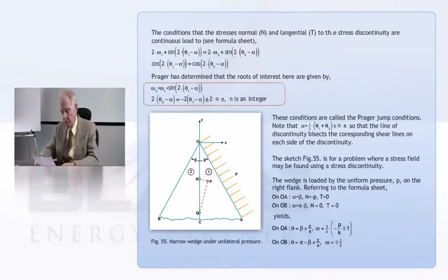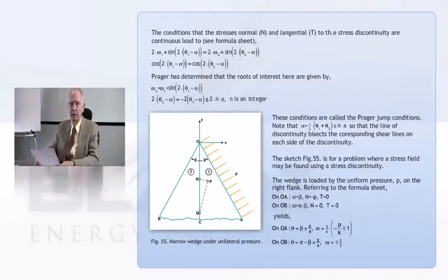The interesting thing about that is that the discontinuity, when you work things out, splits the angle between the corresponding shear lines. And that's very handy because geometrically you can work problems without thinking. And that's the next thing that we're going to do now, is we're going to look at the first thing that I would call a real solution up to now.